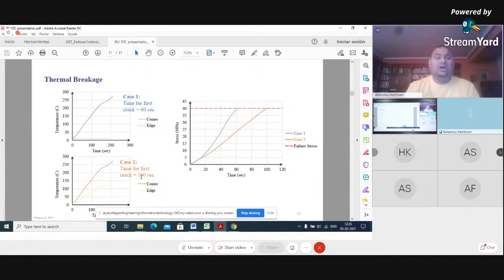around the glass. So actually these experiments are conducted to understand the behavior of glass once it is subjected to fire, because ultimately what we need to do is make a glass which is fire retardant. So we must understand what is happening within the glass so that we could start thinking about what should be done on the surface of the glass or within the glass, so that this phenomenon can be avoided, can be delayed, and we could have a fire retardant glass. So these experiments were conducted in order to have this information.